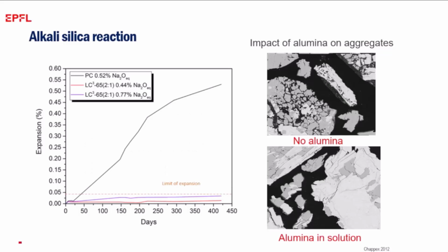So suppression of alkali-silica reaction, basically we have a pretty much flat line now. This was our results after 1.5 years in alkali solution. We now have results out to about 6 or 7 years, and we still see no expansion. And we know from a previous study we did earlier in 2012 that the presence of even very low concentrations of alumina in solution really suppresses the dissolution of the aggregates. So you're suppressing the reaction at source by the presence of alumina, stopping the silica dissolving.